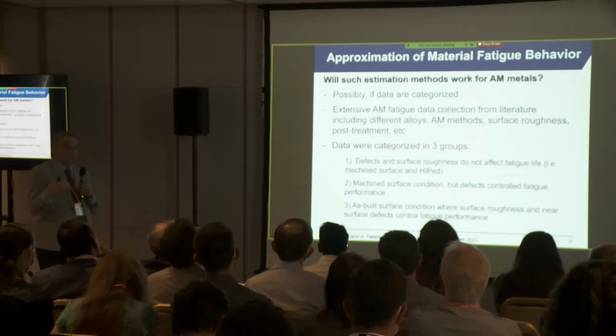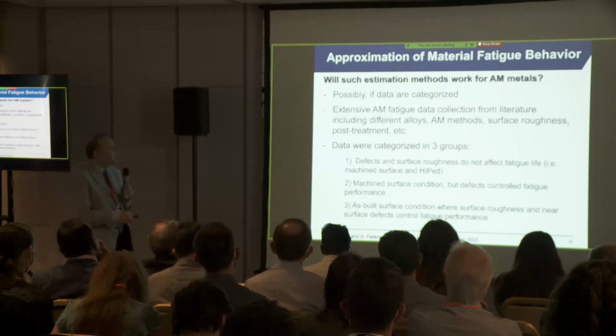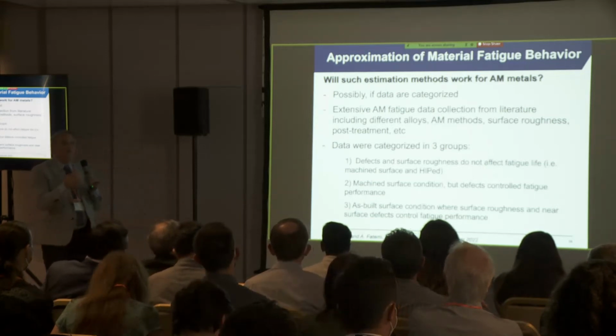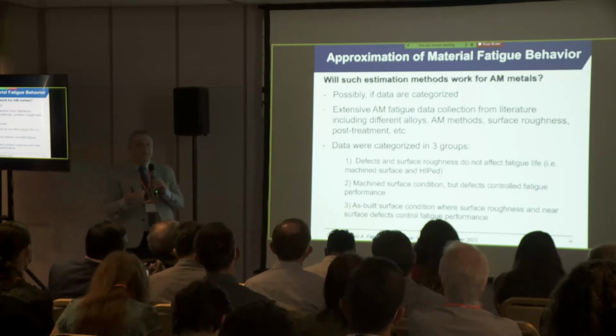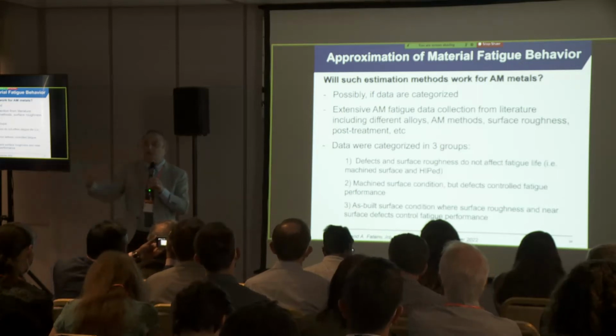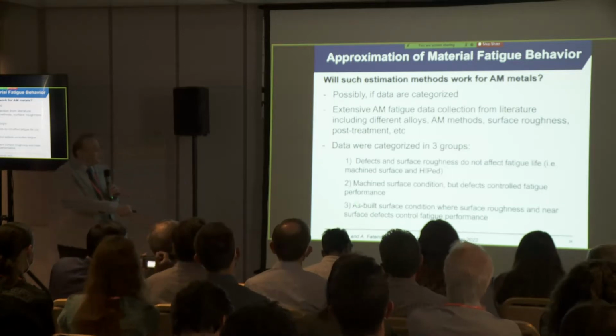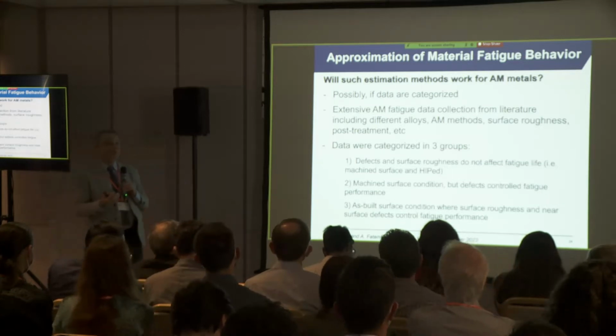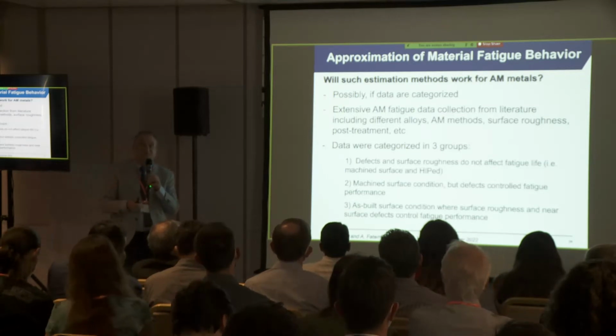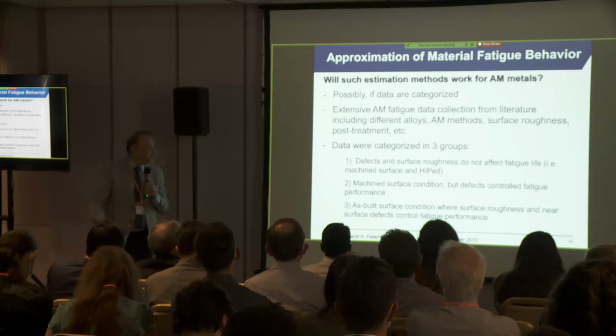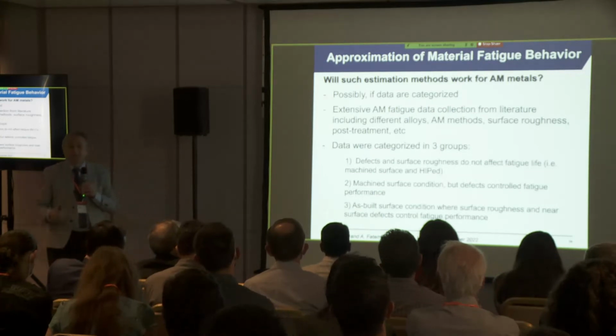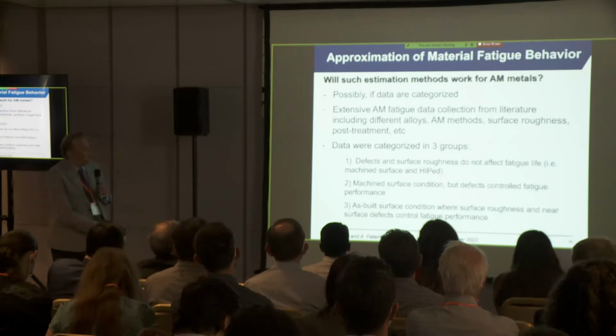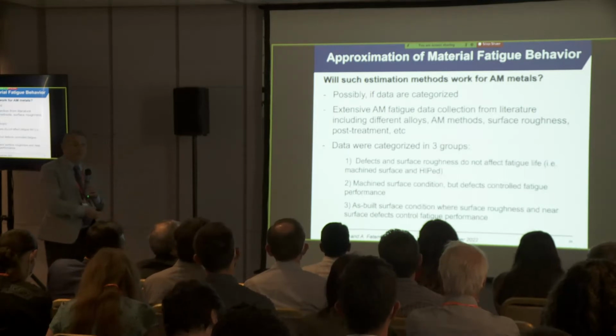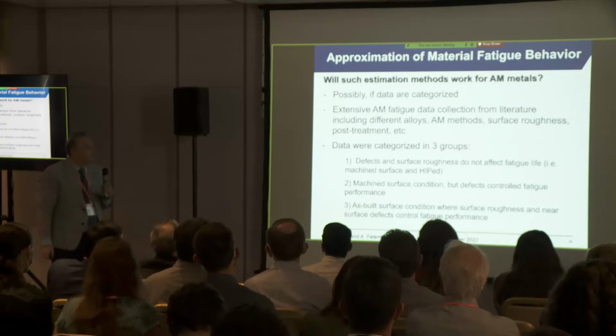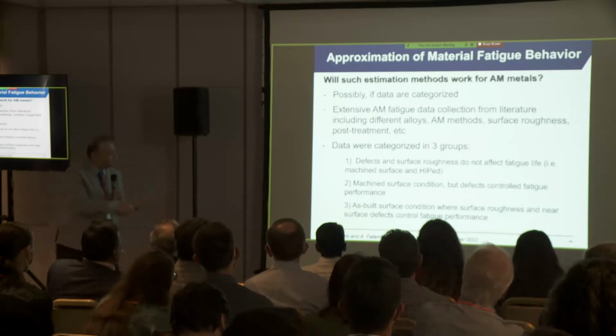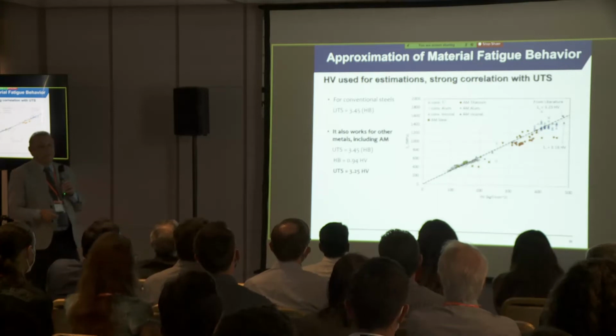Unless you classify the data. So we classify the data based on situations where defects or surface roughness do not control fatigue performance. And then the second group of data, these are situations where the surface is smooth, but there are defects. And then the third situation is where you have a rough surface. So when you divide the data in that manner, I had a student who collected hundreds of data from all the literature so far and classified the data in this group. And now you start seeing good correlations.